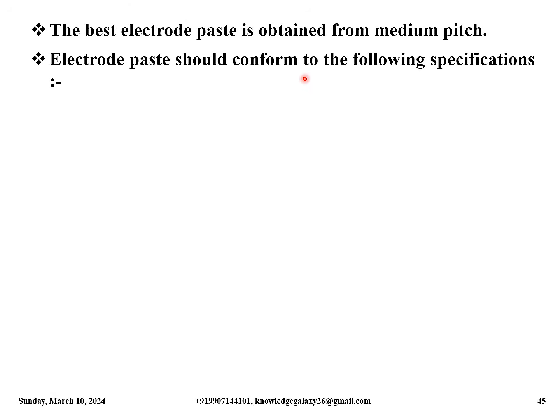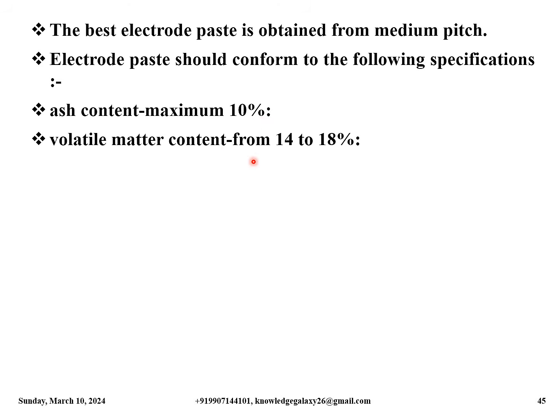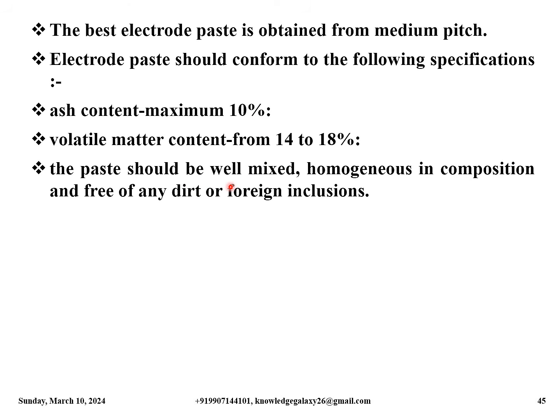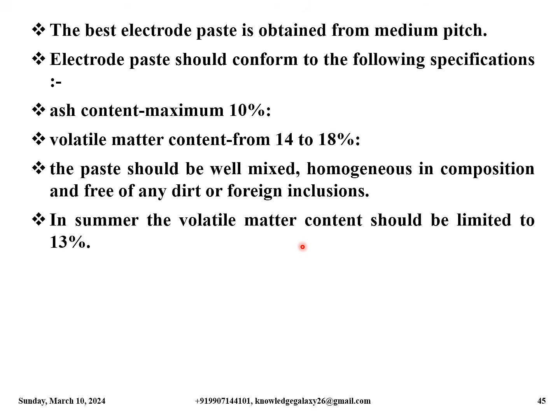Electrode paste should conform to the following specifications. My dear friends, this is one of the most important parts of this presentation. You should watch it very carefully and observe it. Ash content should be maximum of 10%. Volatile matter content should be 14 to 18%. The paste should be well mixed, homogeneous in composition and free of any dirt or foreign inclusions. In summers, the volatile matter content should be limited to 13%.